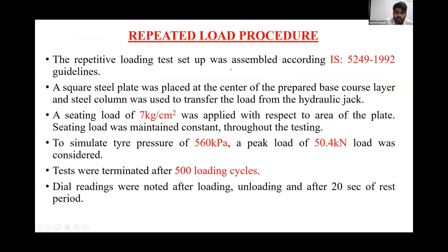Repeated load procedure. The test was assembled as per IS guidelines, and a square steel plate was placed at the center of the prepared base. To transfer the load, the steel column was used. A seating load of 7 kg per centimeter square was applied with respect to the area of the plate. A total peak load of 50.4 kilonewton was considered, and the test was terminated after 500 loading cycles. Dial readings were taken after loading, unloading, and after a 20 second rest period. This is the haversine loading pattern.